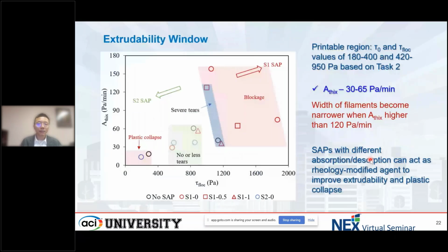And finally, based on this mixture and the mixtures we investigated in the past, we come up with this printability window. The green region means the mixture can be printed with relatively good surface quality, and plastic collapse does not happen. When we use SAP2, it goes to this area. When we use SAP1, it goes to this area. So when we consider using SAP in 3D concrete printing, we definitely need to consider the rheological properties of the reference mixture. In this way, we judge which SAP is suitable for this mixture.